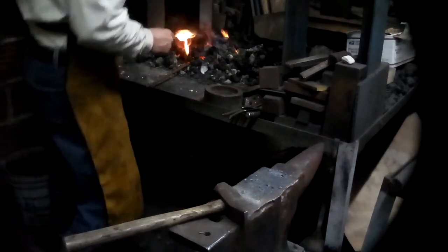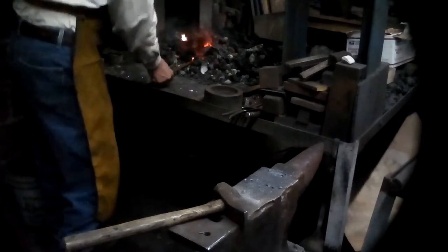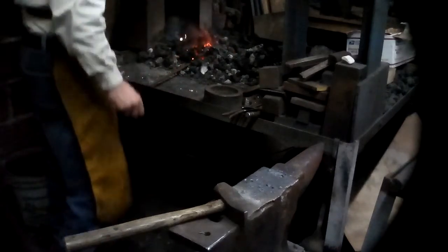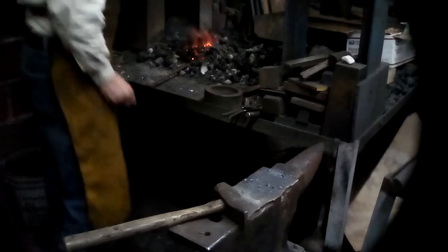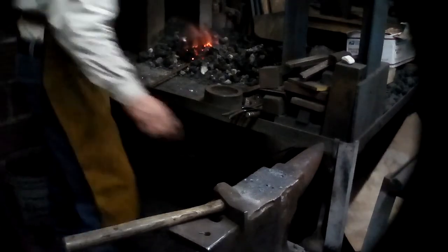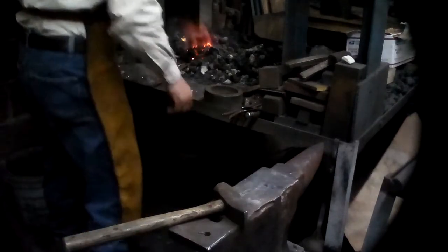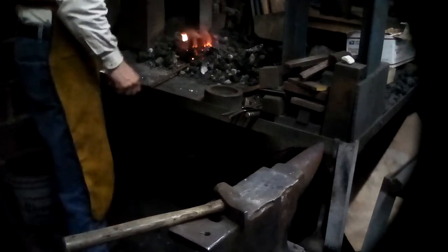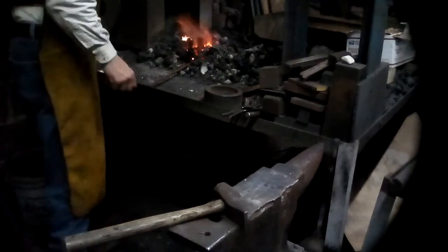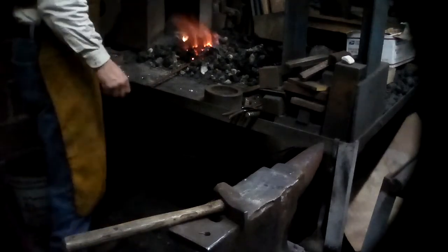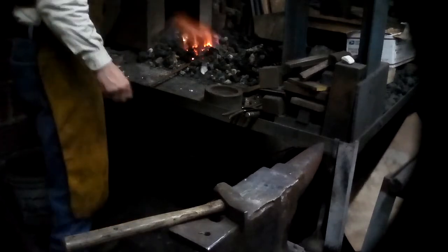But anyway, so now I put this in the fire. It's in that central area. It has to get hot enough. The forge welding range for mild steel is somewhere around 2,400, 2,500 degrees.